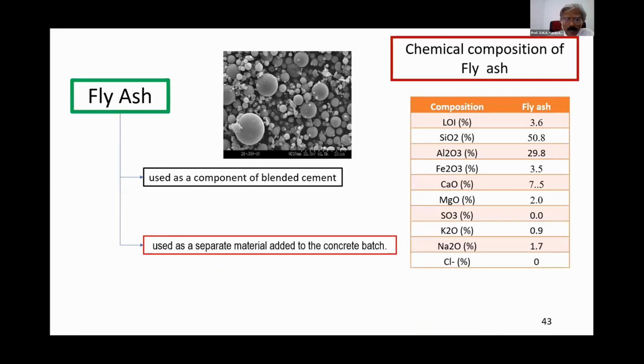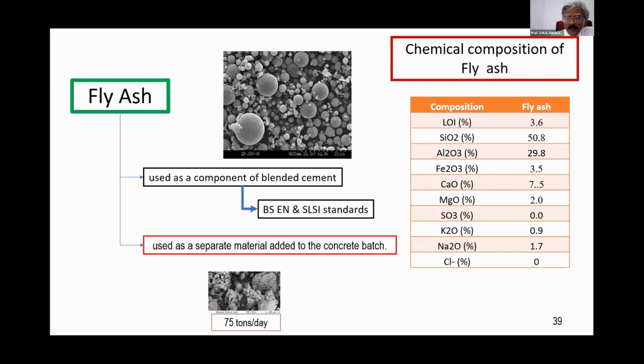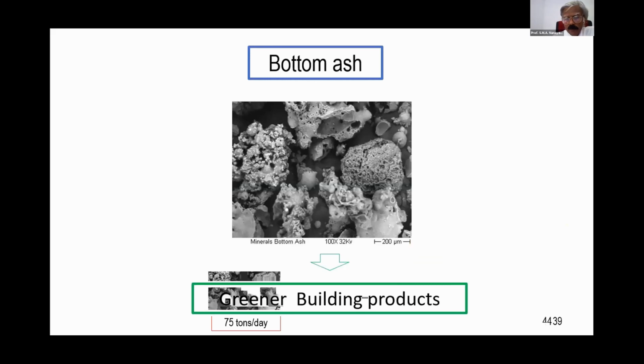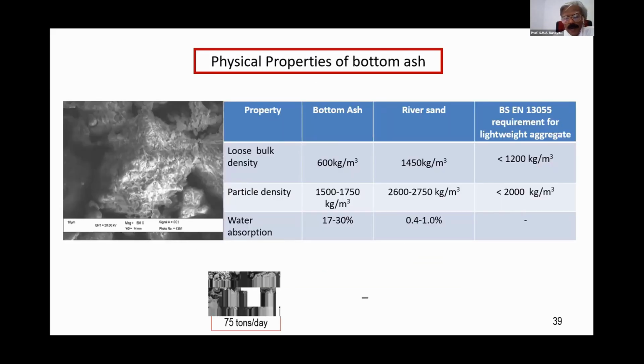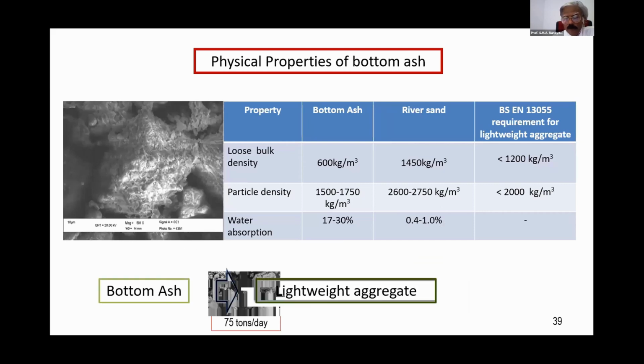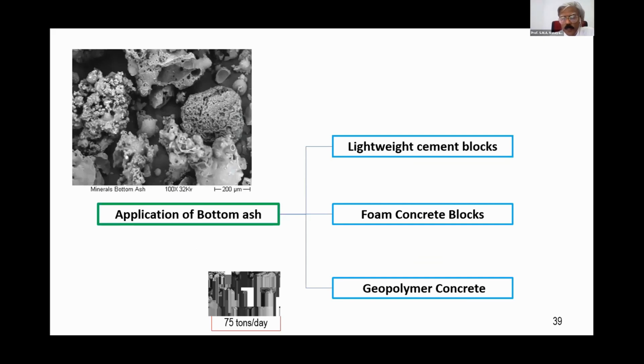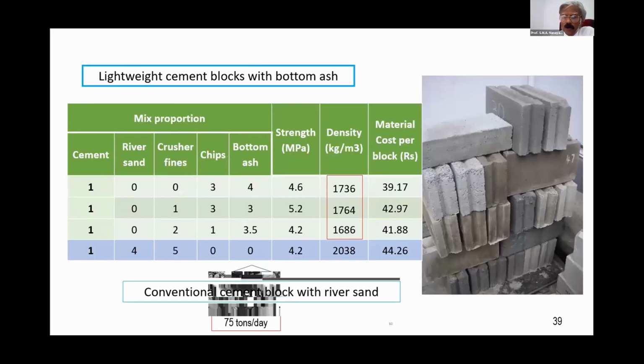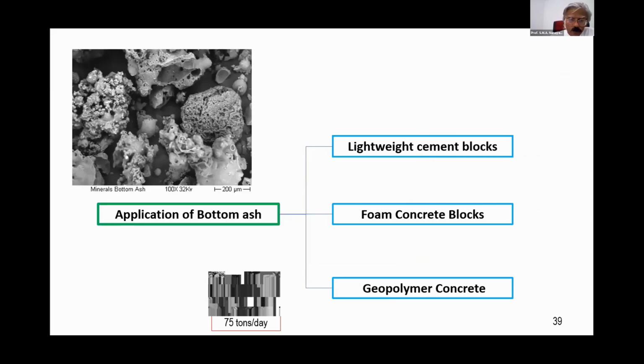So fly ash can be utilized as a component of blended cement, and also we can use it as a separate material in concrete. And bottom ash we can use for green products, and it can be considered as a lightweight aggregate if you consider the properties of bottom ash, and that can be used to produce lightweight cement blocks, foam concrete, and geopolymer concrete.